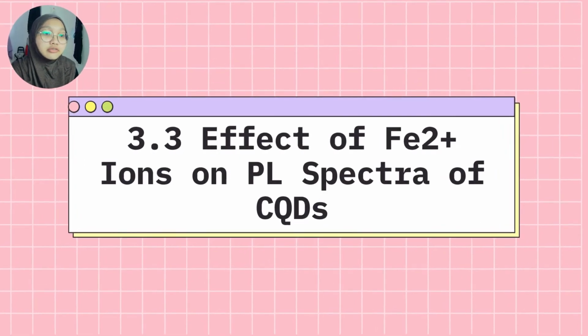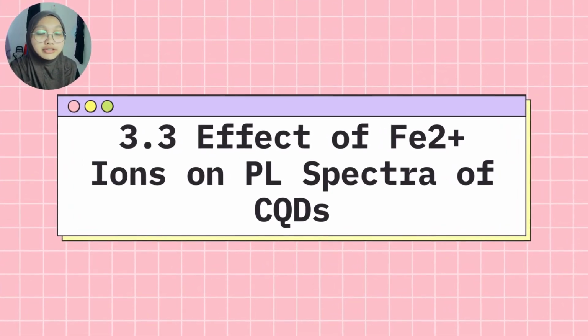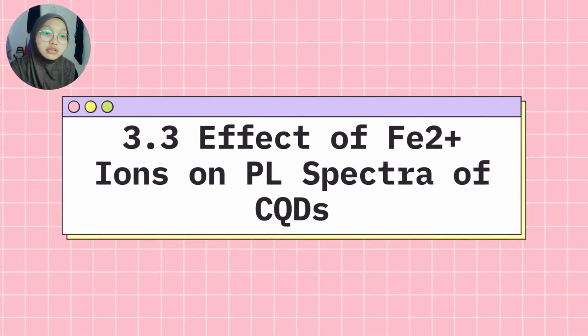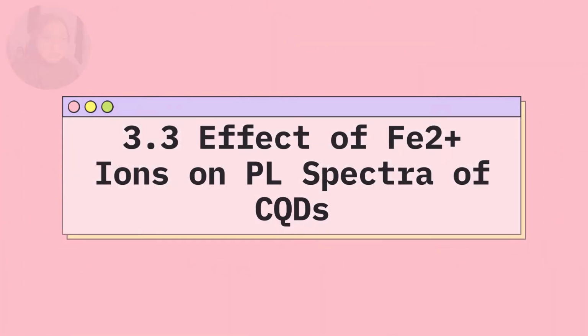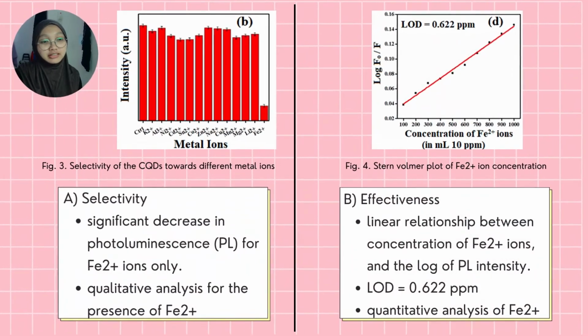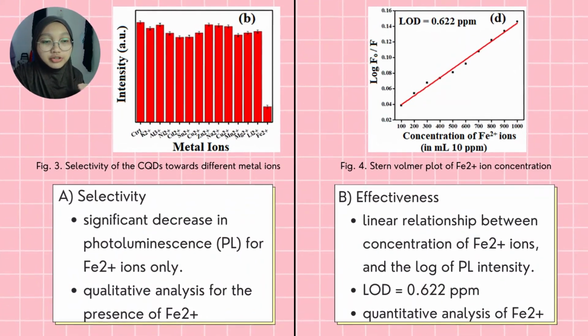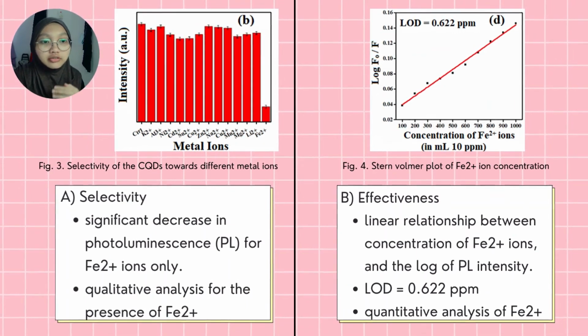The next part is on the effects of iron 2 plus ions on the photoluminescence spectra of the CQDs. So here the CQDs will be evaluated on their performance using Fe2 plus that is present in water and real samples. The first aspect is its selectivity. We want to know whether the CQDs is responsive to any metal ions or is it selective only to the presence of Fe2 plus ions. So based on the photoluminescence spectra, there is a significant decrease in intensity for Fe2 plus only. This means that CQDs can be used for qualitative detection for the presence of this ion. Not only that, it can also be used quantitatively to determine the concentration.